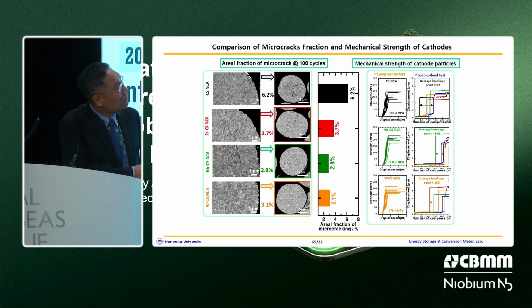And as you can see in the unload test result, the niobium-doped cathode can tolerate pulverization up to about 200 cycles, whereas the baseline and tungsten-doped cathode materials collapsed after 92 and 169 cycles respectively. Based on this result, we believe that the improved mechanical strength of the niobium-doped cathode can suppress electrochemically induced microcracking and thus improve the long-term cycle life.